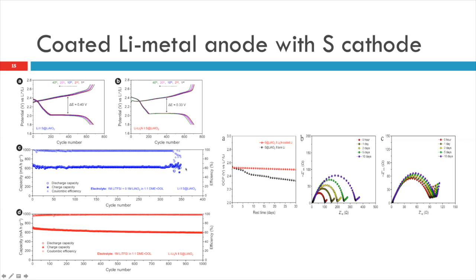But the main problem is the sulfur dissolution, because we already talked about sulfur dissolution being a problem. When you make a cell with an electrolyte which is slowly dissolving, even if you are not charging or discharging, keeping it on a full charge state, it starts slowly dissolving because of chemical reactions. We looked at it up to 30 days, 60 days, to see which one is giving better results. So we have seen that our coated lithium metal is giving better surface protection, and self-discharge is very restricted right now. And the values are also very good. If you look at it, around 90 to 100 ohms after 30 days is observed for the internal resistance on the lithium side, which is good for the cell.